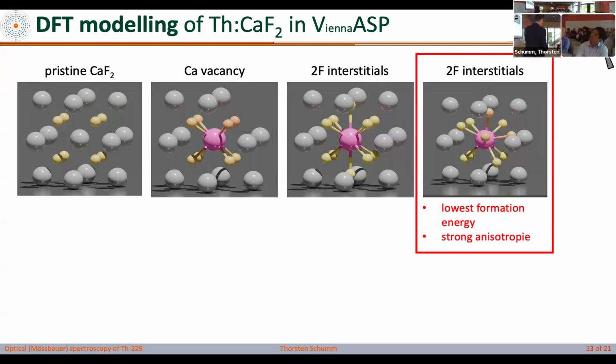And I can ask them, okay, what is the most likely one? And they say, I have to calculate the formation energy. They do that, and it turns out, okay, this one has the lowest formation energy, so we believe this is what's happening in the crystal. And just by looking at it, you see this kind of breaks the crystal symmetry, which is good, because